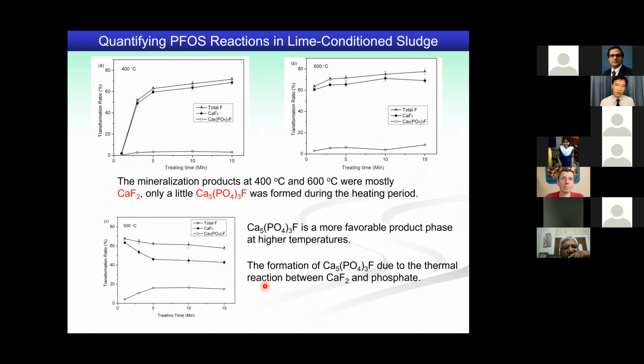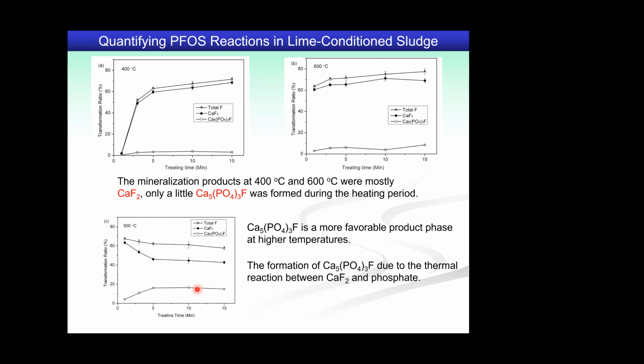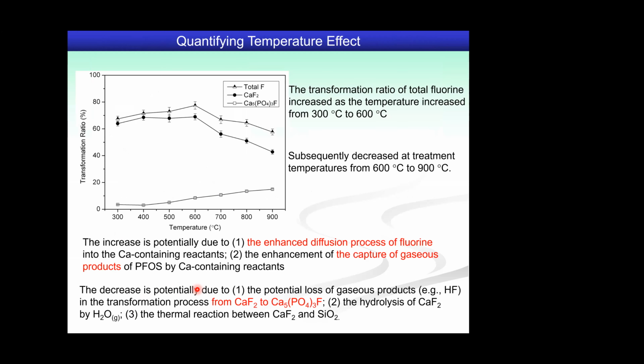Okay, so now let's look at the real sludge. For the real sludge, at 400 degrees Celsius and 600 degrees Celsius, the overall fluorine fixing rates are pretty much consistent with calcium fluoride, which means the calcium fluoride mechanism really stabilizes the fluorine at those temperatures. Your so-called fluoroapatite is there, but it's not the dominant one. But when it goes to high temperature, say incineration, the situation becomes a little bit unexpected, because at 900 degrees Celsius, over relatively longer time, the calcium fluoride generation rate actually decreases, corresponding to an increase in fluoroapatite. That's thermodynamics. So you need to be very careful when you're at very high temperature. You need to know what the dominant phases are that help you do your work.